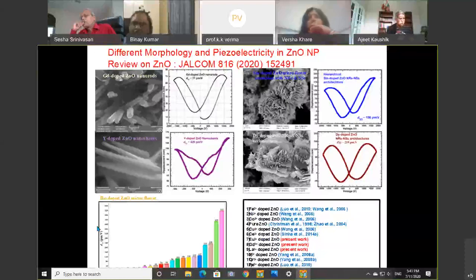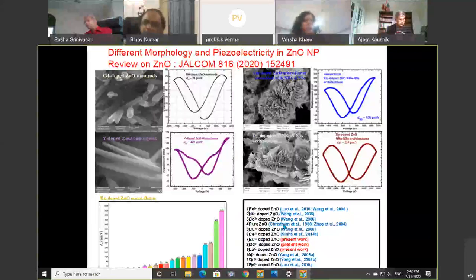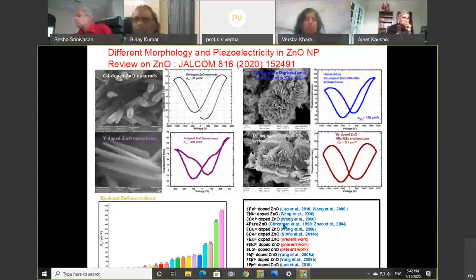We have shown that because of different types of morphology, we are getting a high value of D33, from 5 to 10 to straight away a few hundreds in the case of ZnO. Now come to another picture, where we have used single crystals of PMN-PT and KLN and so many different ceramics, like this one and this one, to make nanoparticles.